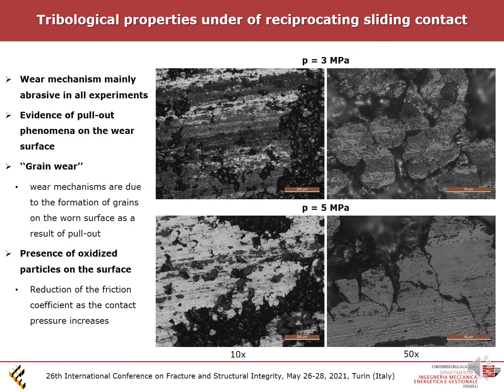In fact, for the tests carried out at low sliding speed, that's 0.1 meter per second, the wear mechanism seems to be mainly abrasive throughout all experiments, with evidence of pull-out phenomena on the morphology of the wear surface. In fact, it can be summarized how wear mechanisms seem to be a consequence of the formation of grains on the worn surface as a result of pull-out phenomena observable in all tested samples.